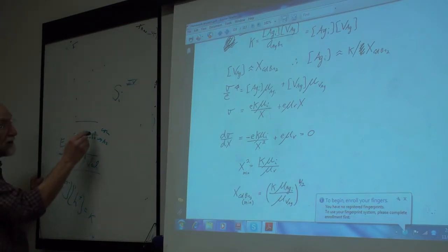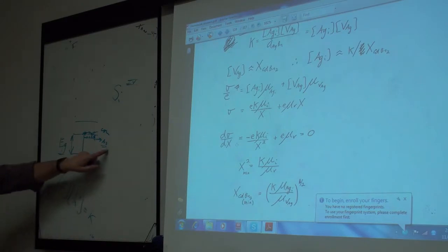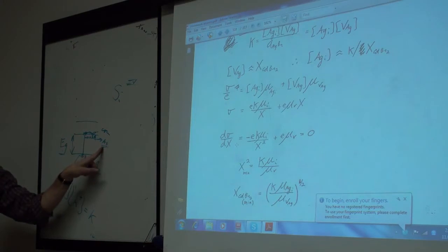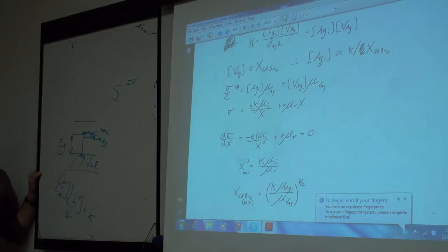That forms up here, this forms an electron. So every arsenic that you add basically gives you an electron, because this is such a small activation energy here. Almost all the arsenics that you add lose their electrons, which then move through the conduction band. Okay, so that's adding an extrinsic defect. And if you add enough arsenic, it's the same thing as here, the conductivity then simply becomes equal to the concentration of the arsenic. Meantime, by adding the arsenic, you're increasing the electron concentration, and you're decreasing the hole concentration, because you've got a whole lot of electrons, they can fall into the holes.